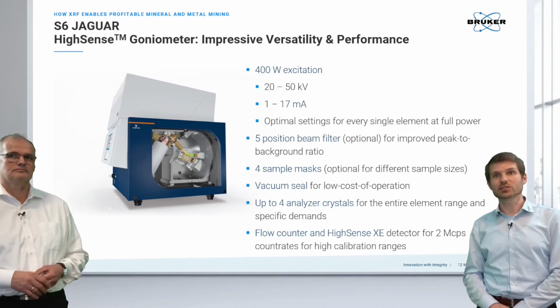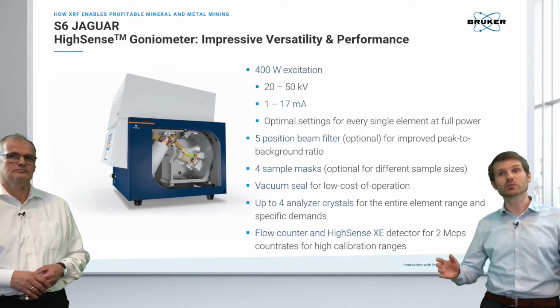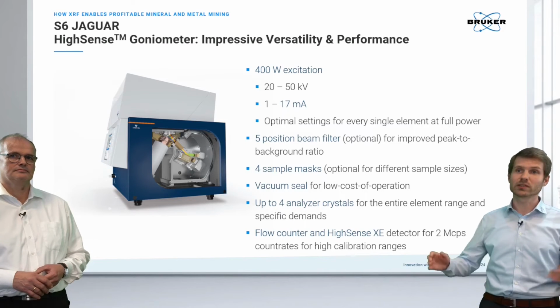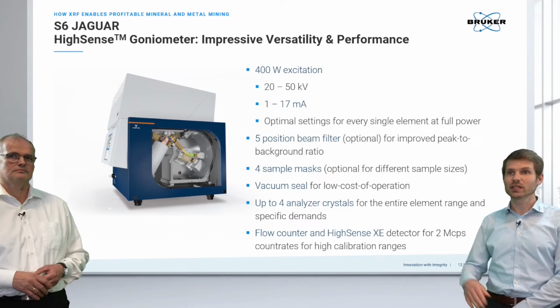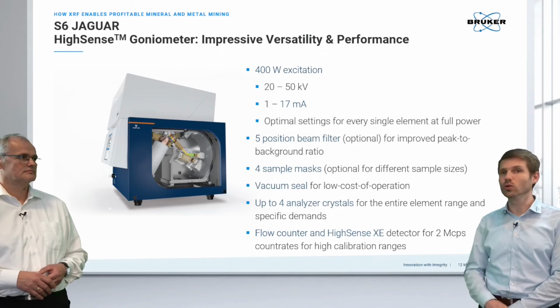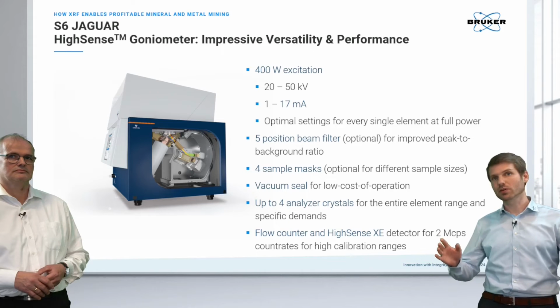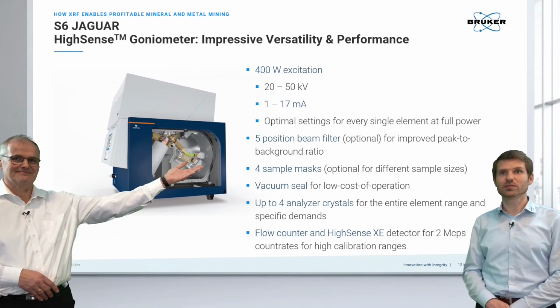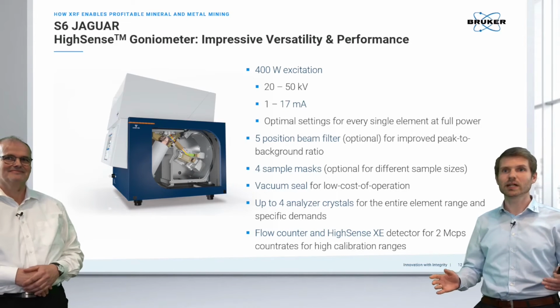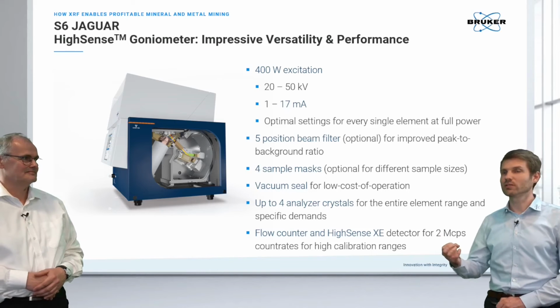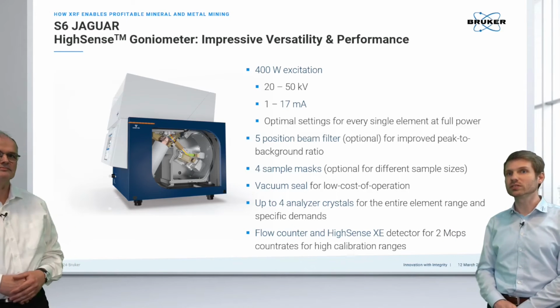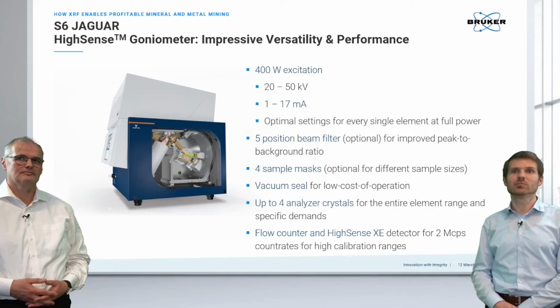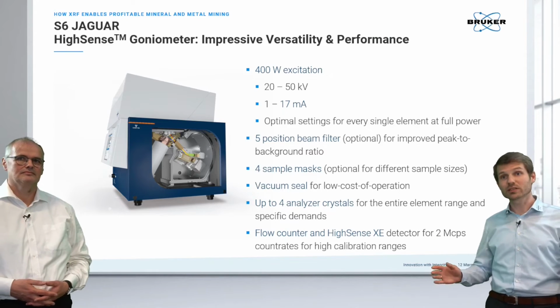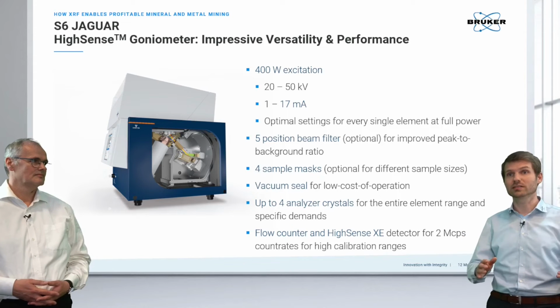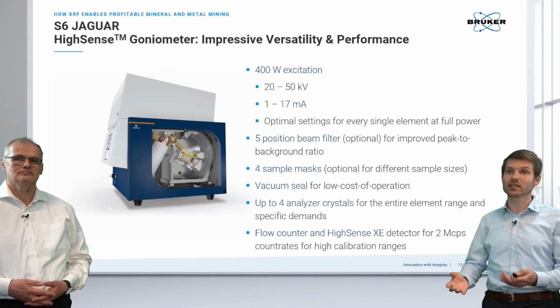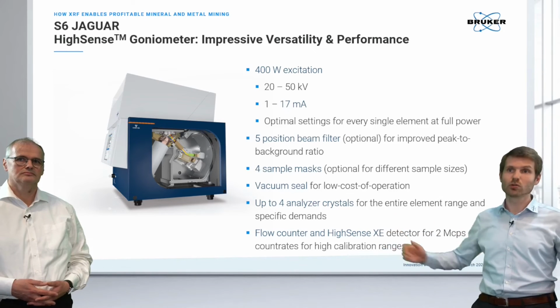So we have the S6 Jaguar here, which is a quite new instrument with a 400 watt tube and with a generator that allows us to use the system even at full power for light elements, so at low kV. It's equipped with a 5-position beam filter. We have a 4-position sample mask changer, and we have a vacuum seal that really protects our system and also reduces the amount of gas that we need, so really reduces the operational costs. So together with the HighSense technology, especially the HighSense XE detector, we can really excel many tasks that can be done on a full-blown wavelength dispersive system.